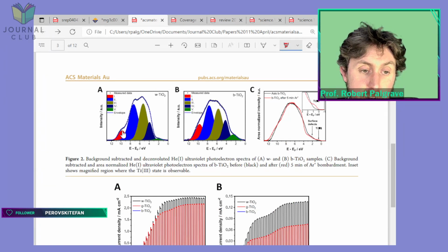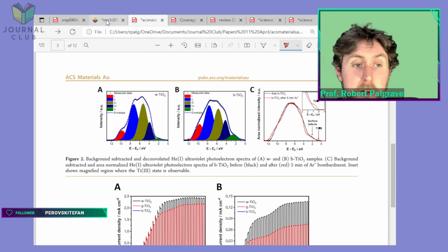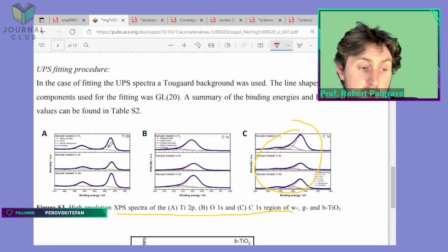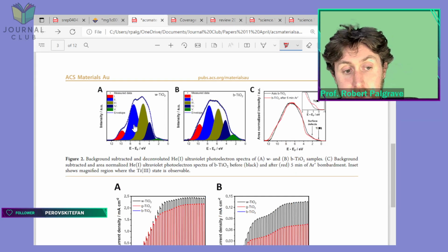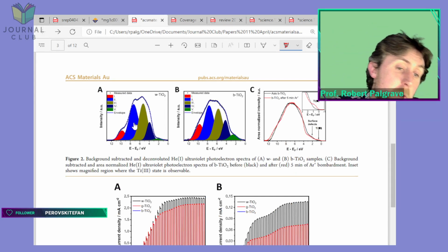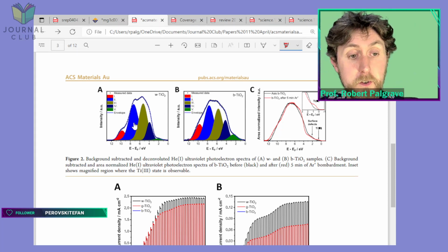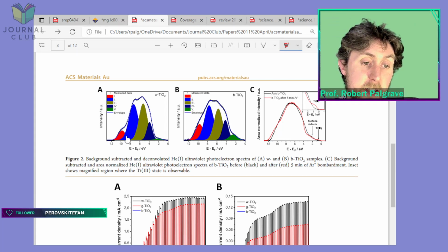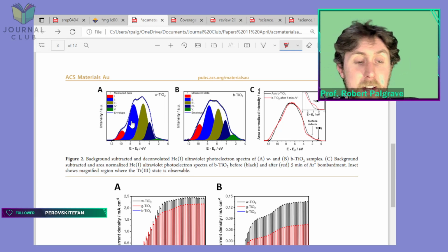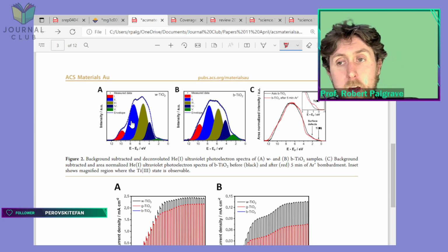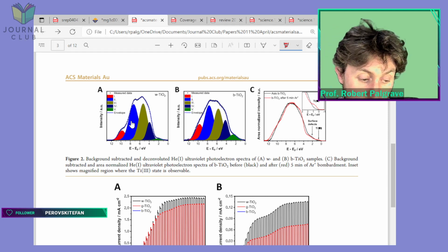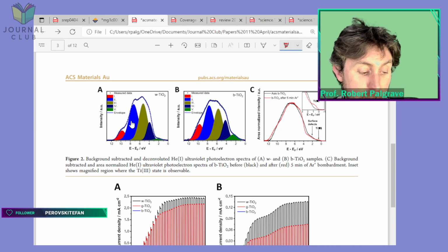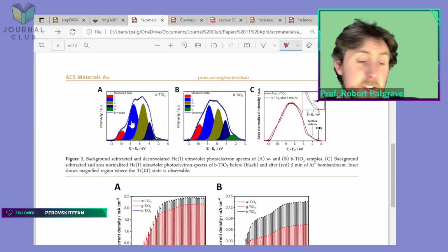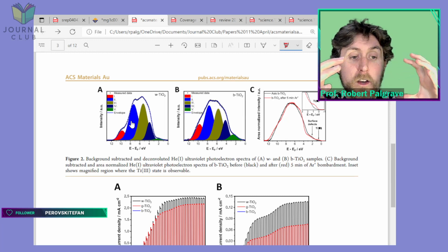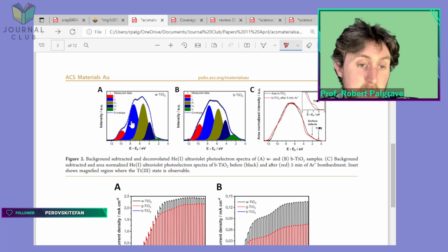Each of these modelled peaks that they've put on there, there's a good reason for that, because the shape here can be understood as a Gaussian Lorentzian peak, and they've used a Gaussian Lorentzian peak here. So they're using the methodology that people use for a core line, but applying it to the valence band. But the valence band is very different to the core line. The valence band is not an atomic orbital in the same way that a core line is. The valence band is a combination of different orbitals from different atoms that are interacting with each other. That's why they're the valence orbitals. The valence is the outermost orbitals of the atoms, which are interacting with each other. That's what chemistry is. That's what the bonds are.